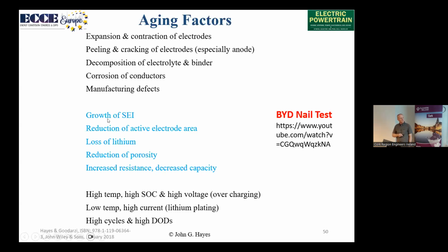We will get growth of the SEI layer. We'll get reduction of the active electrode area. We're going to get a loss of active lithium. We're going to get a loss of porosity. And that's all going to result in increased resistance and decreased capacity of the cell. These are all caused by high temperature, high state of charge, high voltage, overcharging, low temperature, high current, lithium plating, high cycles, and high depth of discharge. All these things are acting to kill the pack. So every time you do that wonderful high power charge up the Midlands, you are working to degrade the quality of your pack. Low power discharges are better, in mild temperatures.